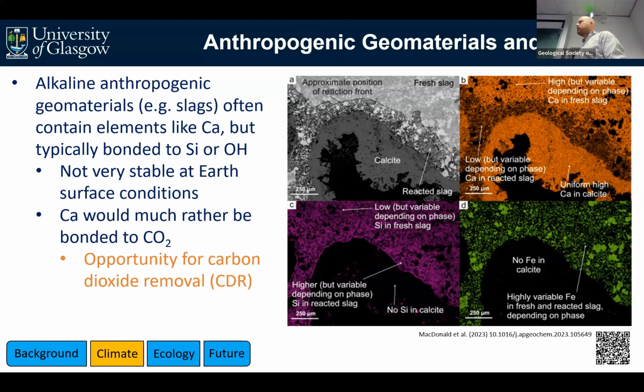Using techniques like scanning electron microscopy, we can look really closely and try and understand what's going on in that CO2 mineralization process. So in the figure on this slide, we've essentially got 4 images from a scanning electron microscope. Panel A, we're looking at just an electron image. The 3 colored ones, B to D, are colored by the distribution of different elements of interest in that same view. In particular, we're interested in panel B, the orange one in the top right. We can see 2 zones of relatively bright color. One up in the top right of the image, which in panel A is labeled fresh slag. We've got another bright orange zone down here, which is labeled calcite, and a darker zone in between. That darker color indicates there's a bit less calcium there.